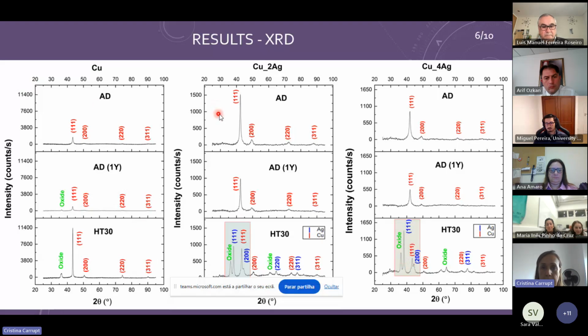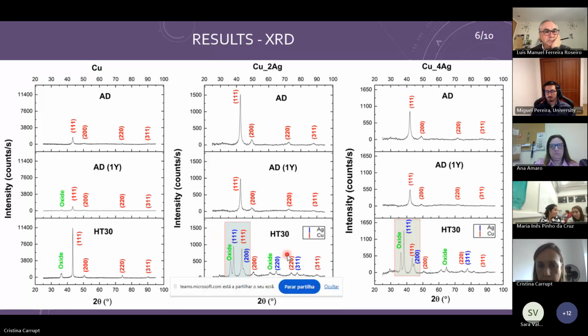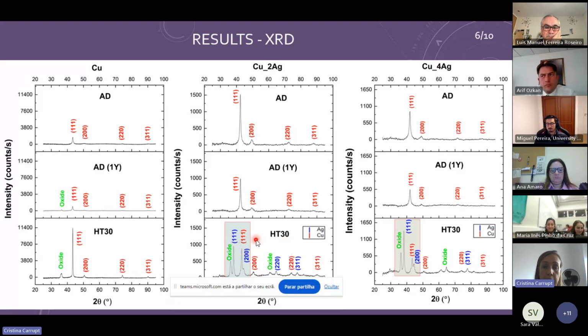We can see that the films have strong orientation according to plane 111. Is it because this specific equipment promotes this, due to the cooling of the substrate? So in this condition, when the surface had lower surface energy, with the addition of silver we have a change. The conditions of planes change. We can see the plane 111 of silver and the plane of copper.